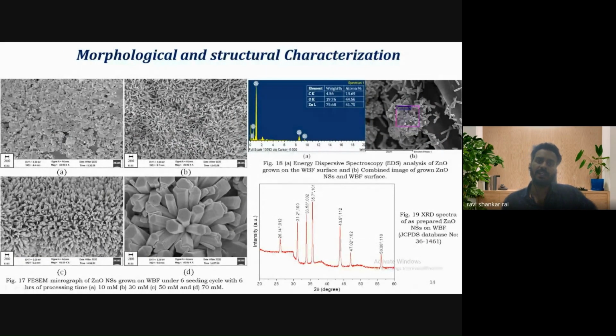So the morphological and structural characterization has been done. This is the pictorial representation showing different combinations of molar concentration. The molar concentration of the growth solution was varied from 10 millimole, 30 millimole, 50 millimole, and 70 millimole. As you can see, for lower molar concentration, uniform growth was not completely achieved. It was just like nanoparticles, not rods, and hexagonal nanorods were not there. Then wires were formed, then hexagonal nanorods started forming, and finally complete hexagonal nanorods developed for 70 millimole.